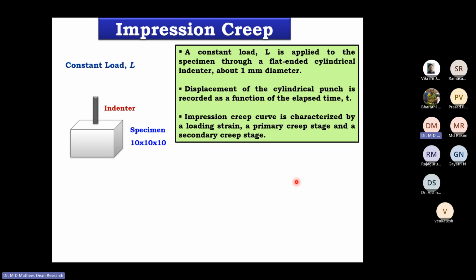So in the impression creep, again, the load is constant, the temperature is constant, and under the action of this constant load, a flat-ended cylindrical indenter, typically about 1 millimeter in diameter, is pushed into this material. The depth of penetration is measured as a function of time. Although the temperature is constant and the load is constant, this indenter will continue to penetrate deeper and deeper into the material. As it penetrates, you measure the depth of penetration at fixed intervals of time.